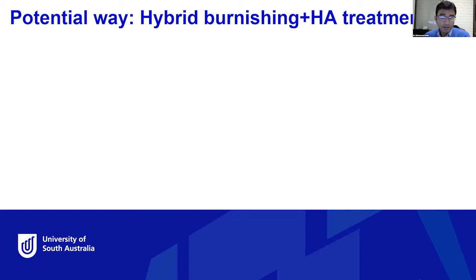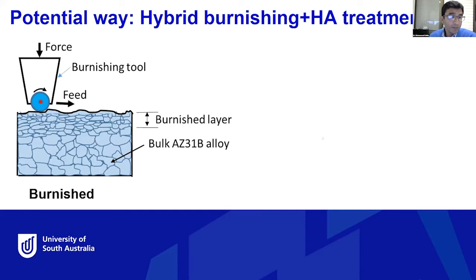Okay, and we found that if we take the substrate of the magnesium alloy and apply ball burnishing, which is a mechanical technique where you apply a force and the ball rolls onto the surface, like cold mechanical working on the material, you can improve the surface texture and also create a microstructural change in the material. By doing that, you can perhaps minimize pores or cracks, and also create some internal compressive residual stress that could potentially prevent corrosion.